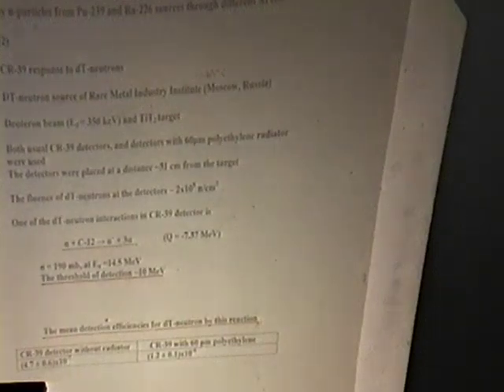DT neutrons also interact with CR39 detectors and produce very different tracks. We exposed our detectors to the DT neutron source of Rare Metal Industry Institute in Moscow, Russia. The deuteron beam with energy 340 keV bombarded the titanium T2 target. We used both usual CR39 detectors and detectors with 60 micron polyethylene radiator. The detectors were placed at a distance near 31 centimeters from the target, and the fluence of DT neutrons at the detectors was near 2 times 10 to the 8 neutrons per square centimeter.